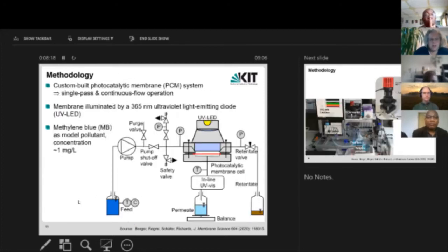So we built a system. There's a schematic of it here and a photo is coming next. It's relatively simple. There is a single pump sucking liquid shown here as our feed, which contains methylene blue dye, which was used as a model pollutant. Concentrations are typically about 1 milligram per liter. And then this contaminated water is pumped through a photochemical cell here, where we have a membrane and a quartz window shown in blue. And above the quartz window, we have a UV LED. I think it's the same one that Lars was using, a Thorlabs 365 nanometer light emitting diode.